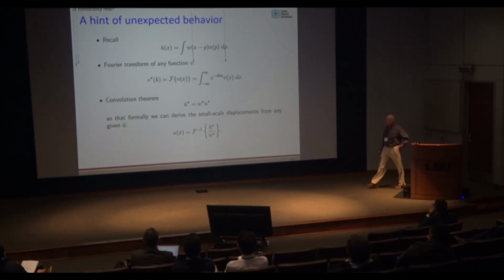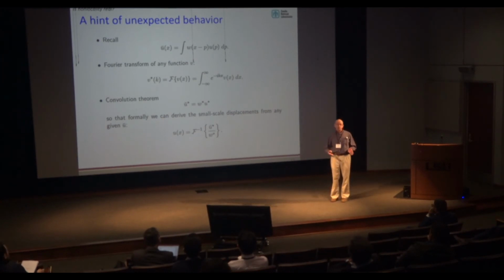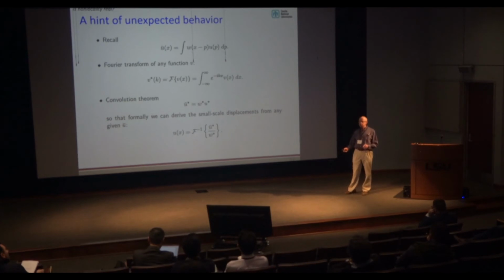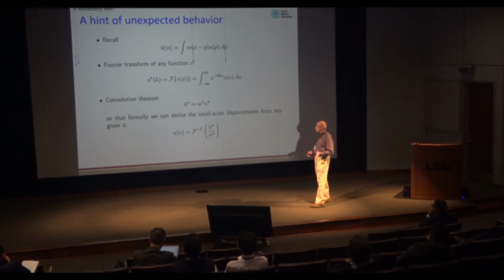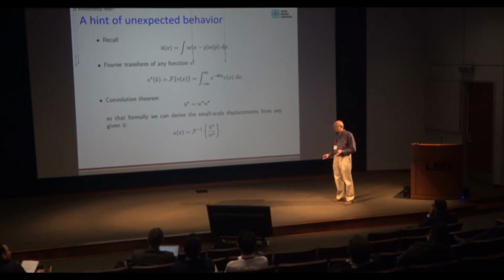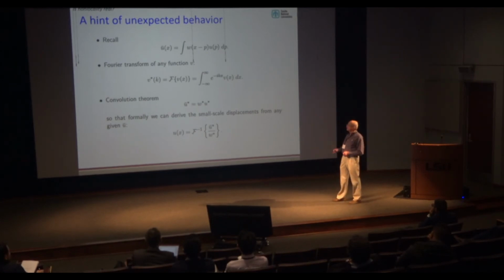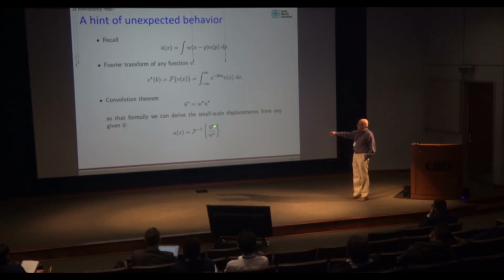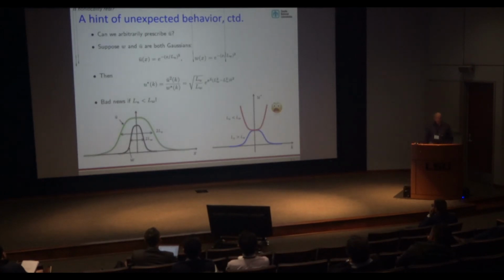An interesting aspect of that example is normally in continuum mechanics, in trying to derive a material model, you would like to be able to prescribe the displacement degrees of freedom everywhere and then evaluate what the forces are. But when we work with the smooth degrees of freedom, it turns out there isn't always a physically realizable small-scale displacement field that generates that. And to see that, you can use the convolution theorem, observe that the Fourier transform of U bar is that of W times that of U. So formally, we should be able to invert the U bar star over W star and come up with a local displacement field. In practice, that doesn't necessarily work too well.